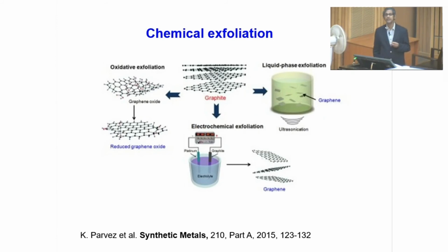These liquids are basically used to reduce the surface energy, the interfacial bond energies between the layers of the graphite. Then you can use shear flow. Once you have a liquid in a mixer jar, the blades move at a very high speed, and because of that a turbulent flow is created, and this flow then allows the layers to be removed one by one.